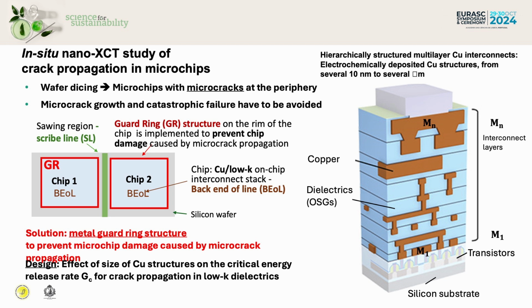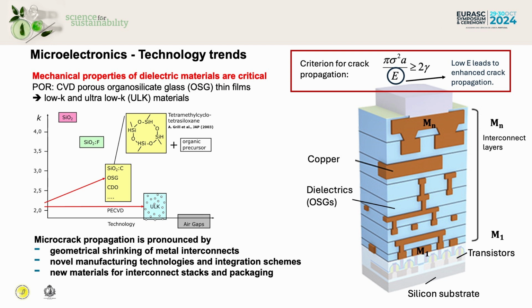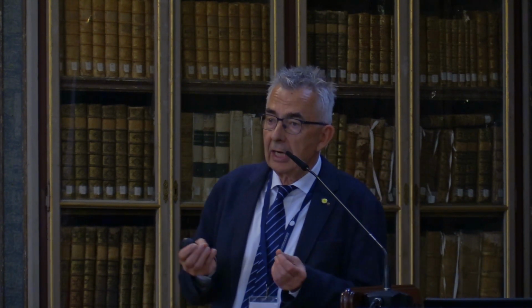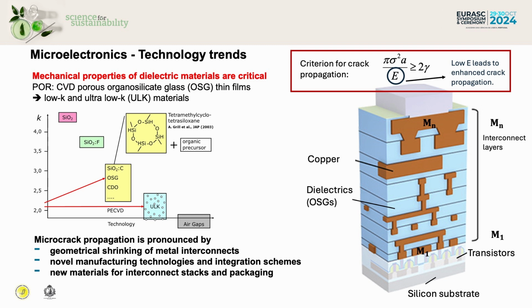What industry is doing, you see it on the left-hand side, is to have at the periphery so-called guard ring structures. And these are structures with a high fracture toughness. The goal is that cracks from the outside, here from the dicing process, are stopped at these guard rings. And why is it particularly important now? It is particularly important because the insulating material in microelectronics was originally silicon oxide, but in recent years, more and more organosilicate glass and porous organosilicate glass is used to insulate the copper for performance reasons, because you reduce the dielectric permittivity dramatically. At the same time, you reduce Young's modulus by a factor of 10 or more, and then I remember Griffith: here's the Young's modulus, that means the left-hand side becomes large, and the probability that the crack is propagating is higher.